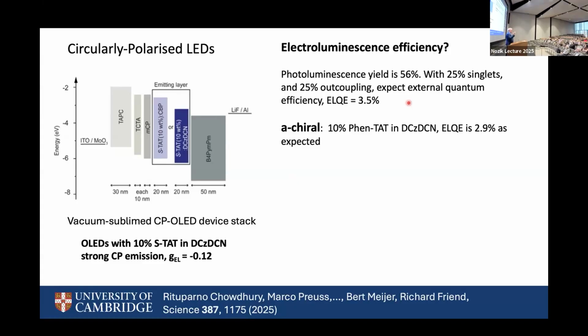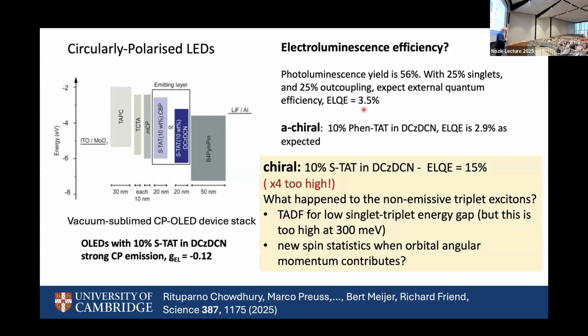And only about a quarter of those will exit in the forward direction. The rest get trapped in plane or head downwards. So with the standard models, we would expect to get an electroluminescence quantum yield of about 3.5%. We measure 2.9% for a material which is not chiral. It's one of the structures I showed you earlier. Really surprisingly, the chiral structure is 4 times brighter.